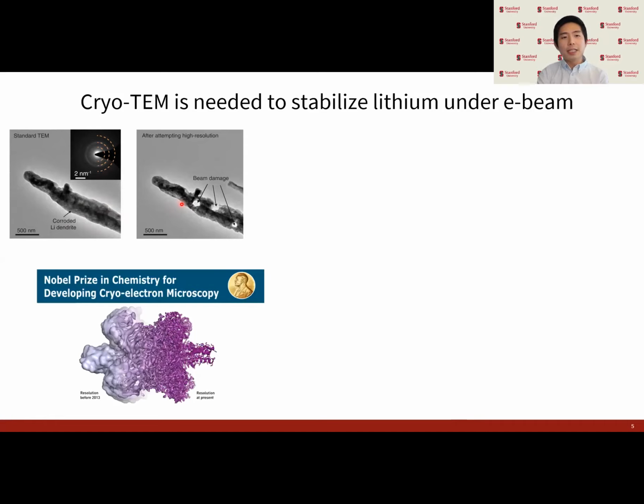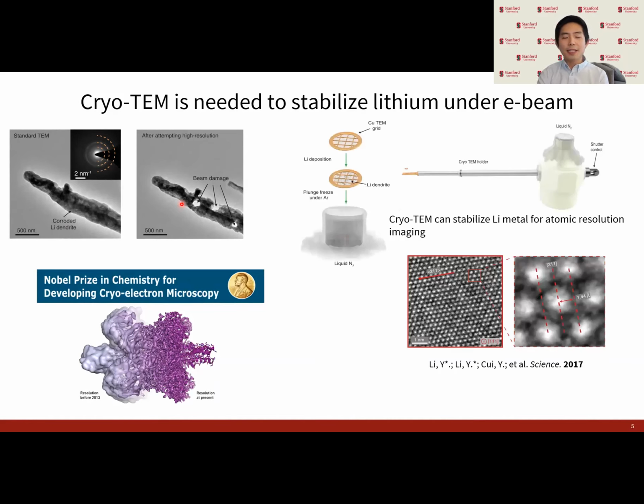Now in structural biology, biomolecules are even more sensitive than lithium. But in 2017, the Nobel Prize in Chemistry was awarded for the technique of cryogenic electron microscopy, or cryo-EM. And what cryo-EM can do is stabilize these very sensitive biomolecules under electron radiation. So colleagues in our group, inspired by this technique, have adapted this method for battery materials, where by opening lithium metal or other lithiated compounds in the glove box and freezing these specimens under liquid nitrogen, we can actually stabilize these specimens under the electron beam and kinetically freeze out any side reactions.